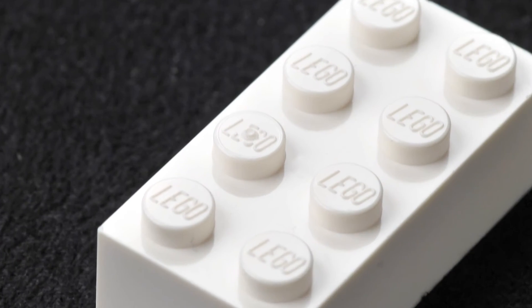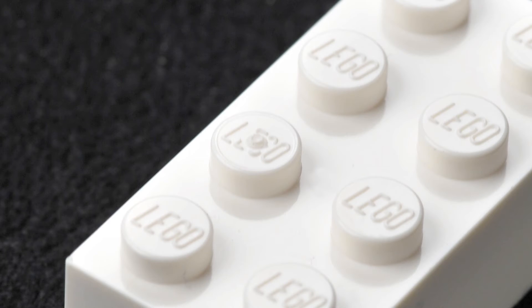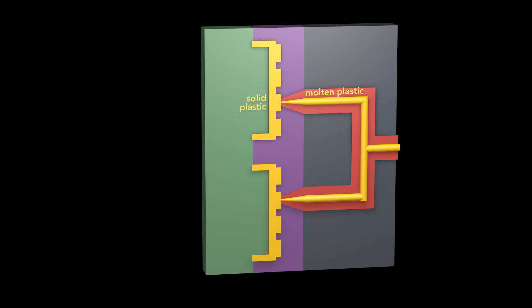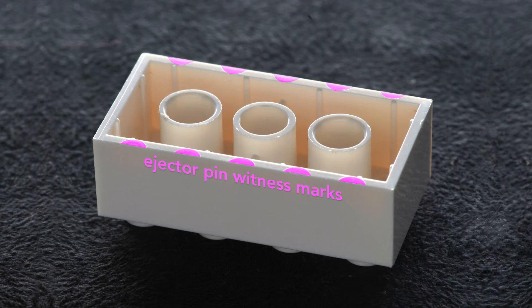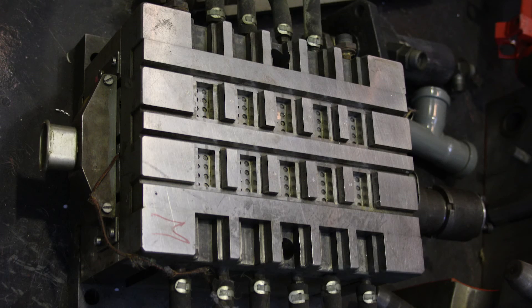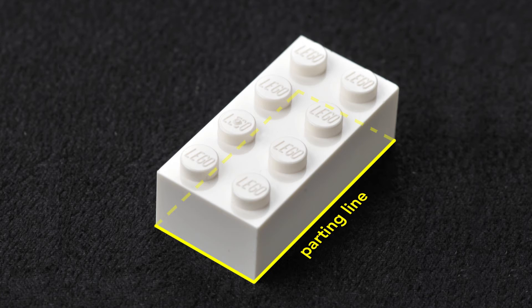One impressive example of injection molding is the Lego brick. You can see the injection point in the middle of a stud, but this is not from a gate or a sprue — Lego molds use hot runners. Hot runners are a heated distribution network that keeps plastic inside the runners molten while the plastic in the mold solidifies. This leaves no gates or sprues to be removed; the molded bricks are ejected ready to use. The downside is that this setup is more expensive than a traditional cold runner system. On the bottom edge of the brick, you can see ejector pin witness marks. What's most clever is where Lego designs their draft angle — the outside of a Lego brick must be square, so if you cut a Lego brick in half, you can see that the inner supports are thicker at the top than at the bottom, with a draft angle of about one and a half degrees. This helps the ejector pins push the brick off the mold. The core half and cavity half of Lego molds are designed so that the parting line is at the bottom edge of the brick, which hides the parting line.